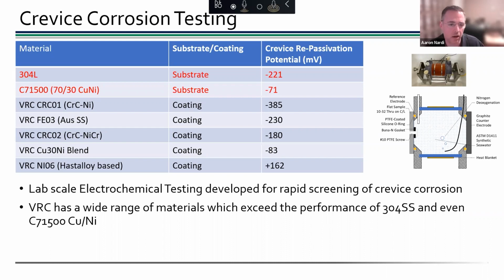So if we start to look at our coatings, we have an austenitic stainless steel, which is very similar to that 304. The chrome carbide nickel is actually a little worse in crevice corrosion because it does have that pure nickel in it. Nickel chrome's a little better. That's the CRC02 material. And then you can see the best materials are actually the copper nickel, similar to the wrought material, and then a Hastelloy-based material, which has much superior corrosion performance in comparison to the others.